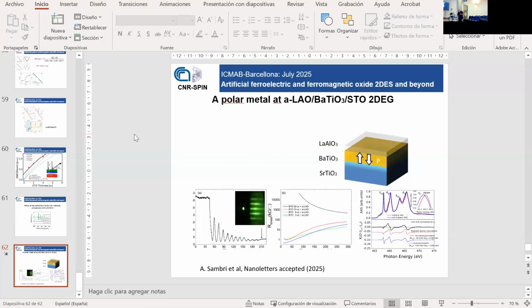Yeah, if I understand well, the question is very relevant, in particular if the 2DEG is really two-dimensional. These are not two-dimensional, they are quasi-two-dimensional, in the sense that the confinement, which is a few nanometers, is not one layer. The confinement, in comparison to, for example, the mean free path, is smaller, and the superconducting coherence length is smaller. So it's more correct to say quasi-two-dimensional. It's not really two-dimensional, but if it were two-dimensional, of course, step edges would matter.